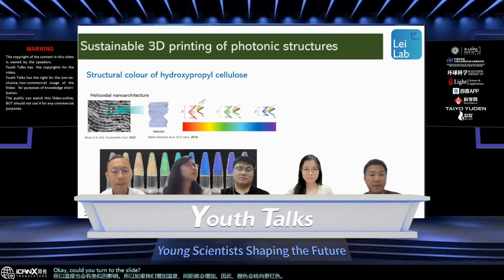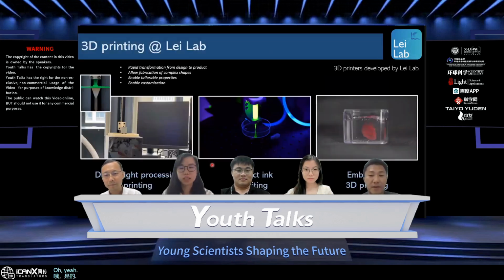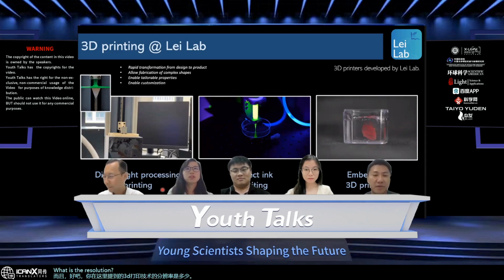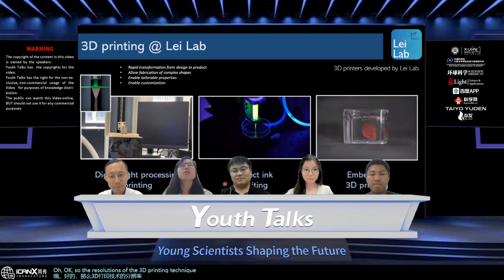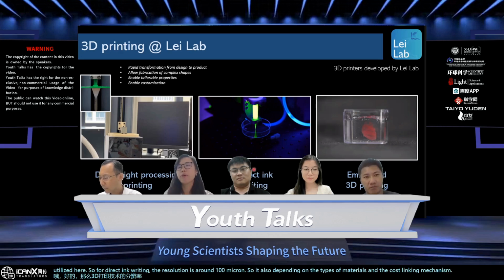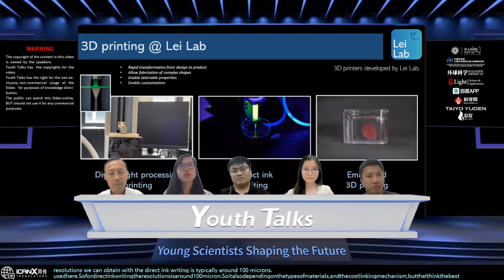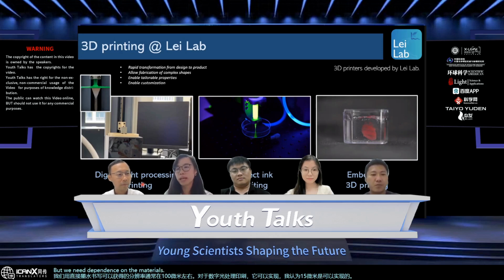Okay. And could you turn to slide 5? Yes. What is the resolution of the 3D printing techniques you mentioned here? So for direct ink writing, the resolution is around 100 micron. It also depends on the types of materials and the cross-linking mechanism, but I think the best resolution we can obtain with direct ink writing is typically around 100 micron. For digital light processing printing, I think 50 micron is achievable, but it really depends on the materials we would like to print as well as the cross-linking mechanism.